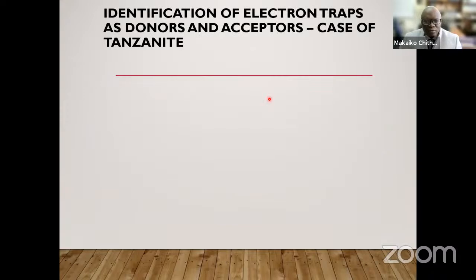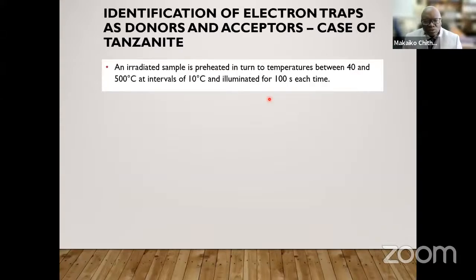Going back to the case of tanzanite, how do we identify which ones are acceptors and which ones are donors? You can do that using this process. If you irradiate a sample and then you preheat it, then after each preheating, you expose it to light. Then you irradiate the sample again, change the preheating temperature, expose it to light again, and keep repeating this process until you have removed all the peaks that appear in your glow curve. It's a time-consuming process. It's a very long process, but it gives useful information.